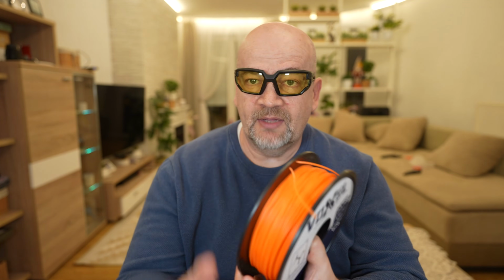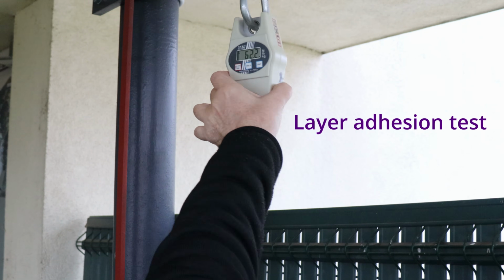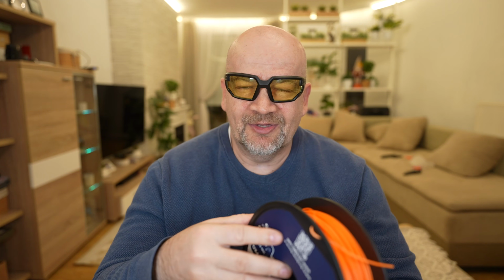Again, this was much bigger work than I planned. First, about PLA filament. This is a quite good PLA filament, mechanical properties above average PLA. The only thing I don't like here, except the spool I already mentioned, is that I don't have that nice adhesion to the bed. About the flow rate, it is better than average PLA, something similar to Bambu PLA Basic, but not 500 mm per second speed. Of course, I can imagine some setup where it can reach 500 mm per second, but that's not an average setup.